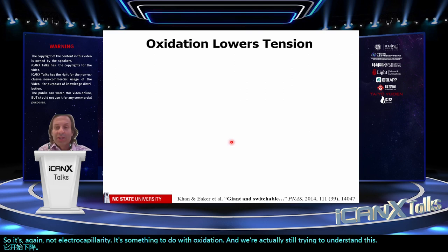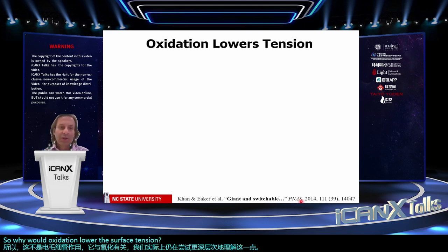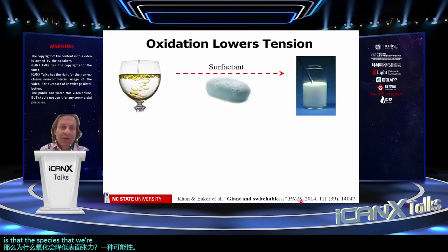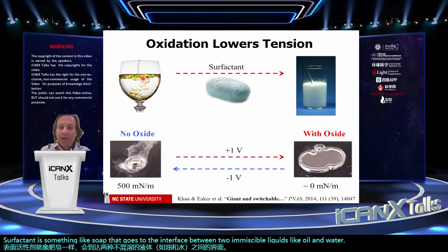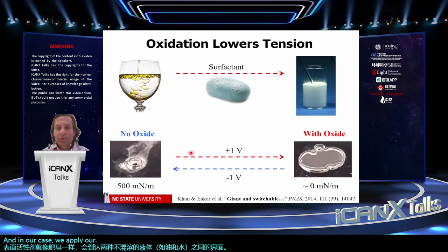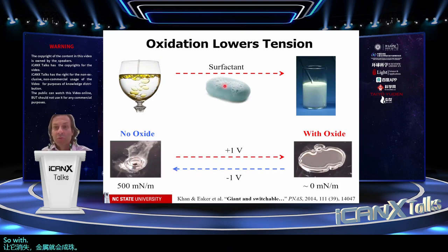So why would oxidation lower the surface tension? Well, one possibility is that the species that we're depositing are kind of like surfactants. Surfactant is something like soap that goes to the interface between two immiscible liquids, like oil and water. And in our case, we apply our soap with 1 volt, and we lower the surface tension. We think it's very, very low. And then -1 volt makes it go away, and the metal will bead up. So with soap, it's very easy to put soap into water, but very difficult to remove it. Here, we can remove it or deposit it completely reversibly.